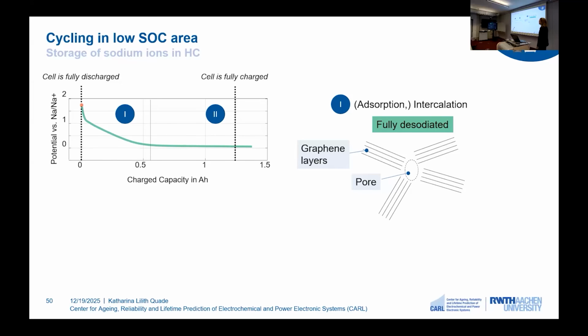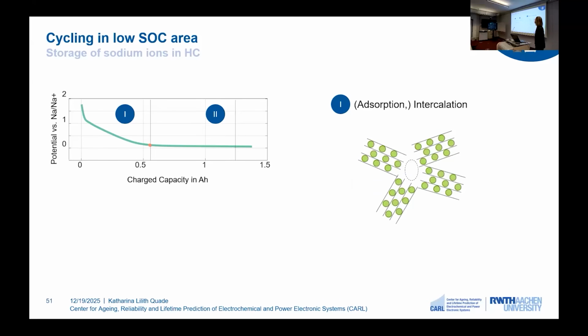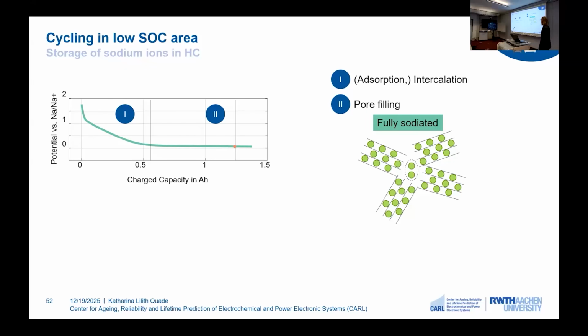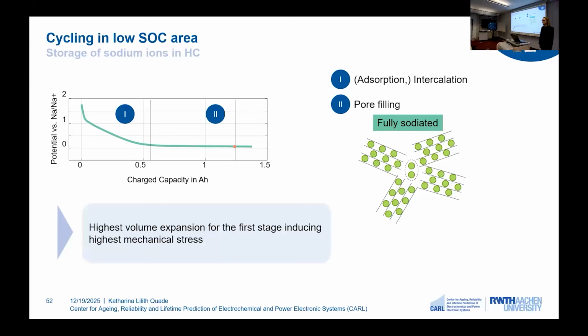Now, let's have a look at what happens when we go from a desodiated state to a more sodiated state. We can see that the sodium atoms intercalate into the graphene layers, and this leads in our schematic to a high volumetric expansion. And now when we go to the second step and we sodiate our anode more, we can see that the pores are filled. However, this does not lead to a high volumetric expansion. So we know from our model that we have the highest volume expansion for the first step, for the intercalation.